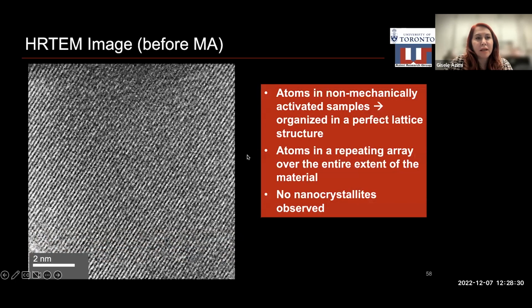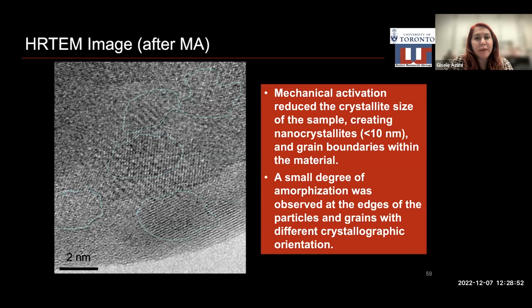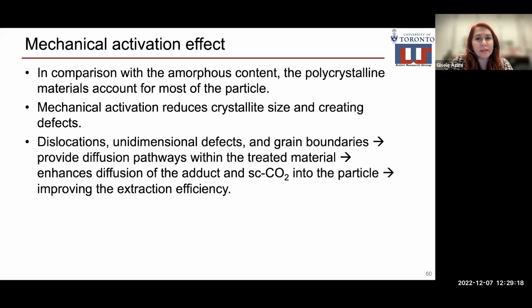We looked at these materials under high resolution TEM. Before mechanical activation, we see that atoms are organized in a perfect lattice array. They are repeating in arrays over the entire extent of the material, and no nanocrystallites are observed. However, after mechanical activation, we observed a reduced crystallite size, nanocrystallites of 10 nanometers or less, and lots of grain boundaries in the material. A small degree of amorphization is also observed at the edges of the particles and grains with different crystallographic orientations. In comparison with amorphous content, the polycrystalline material accounted for most of the particle.